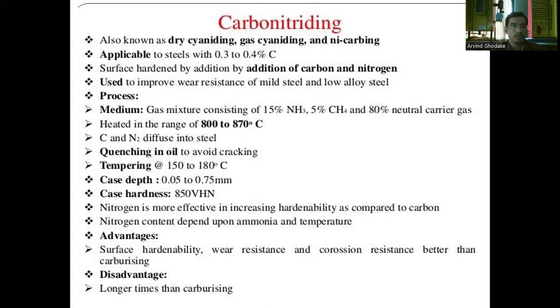The tempering temperature is 150 to 180 degrees Celsius. Case depth is 0.05 to 0.75 mm. Hardness achieved after carbon nitriding is 850 Vickers Hardness Number. Nitrogen is more effective in increasing hardenability compared to carbon, and nitrogen content depends upon ammonia and temperature. The advantages of carbon nitriding are increased surface hardenability, and better wear and corrosion resistance than carburizing. The disadvantage is that it takes longer time than the carburizing process.